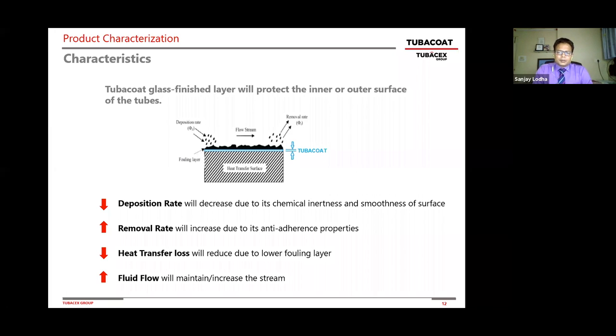When you apply this coating inside the tube, what you see here is that the deposition rate of the particulate matter or the fouling matter will decrease, because the tubes are chemically inert and very smooth, like a glass finish. Also, the removal rate of this fouling material will increase because it will not stick to the surface of the tube. Because of that, the heat transfer loss, which you would have otherwise, will reduce significantly. And since you don't have that fouling and heat transfer loss, your fluid flow, the process throughput, will be maintained at a steady state. That's an important characteristic of the Tubacoat. Next slide, please.